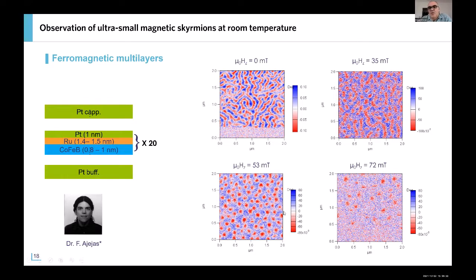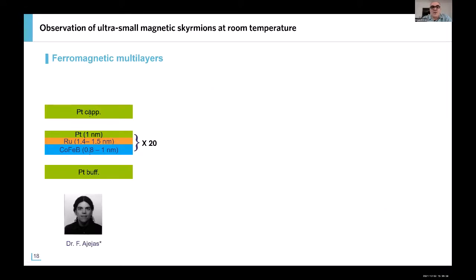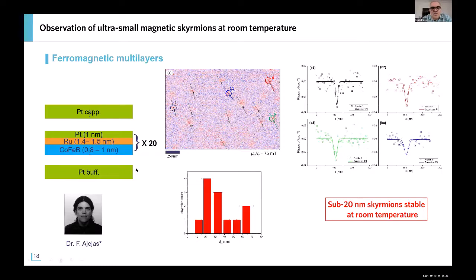But then if you keep increasing this perpendicular magnetic field, you end up with more isolated skyrmions, and the signal becomes very weak because, in fact, they become extremely small. This is because we really optimized all these parameters, PMA and DMI and so on, to get these skyrmions very small. And you see, if we make a line section across a few skyrmions, we can have a peak in the statistic for a diameter that is about 20 nanometer, or sub-20 nanometer skyrmions stable at room temperature, which is, to my knowledge, some of the smallest skyrmions that can be stabilized at room temperature.